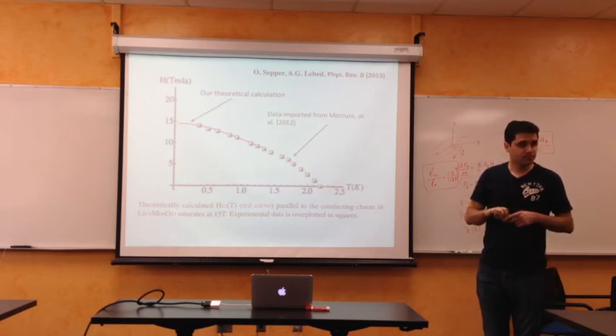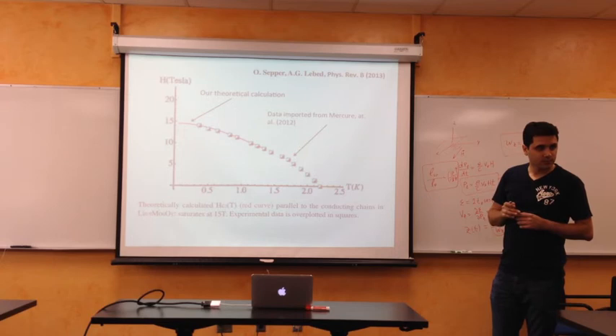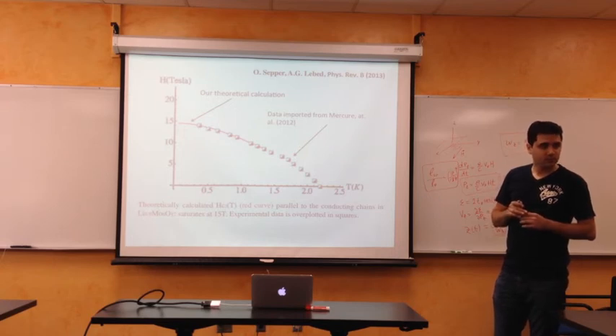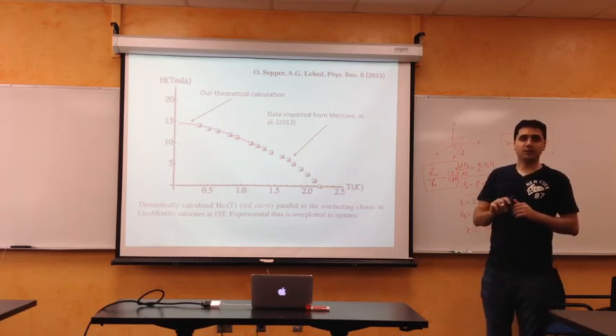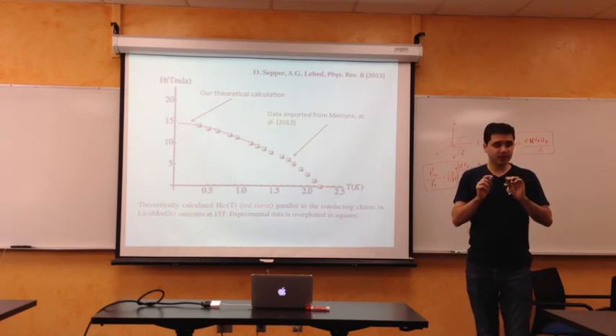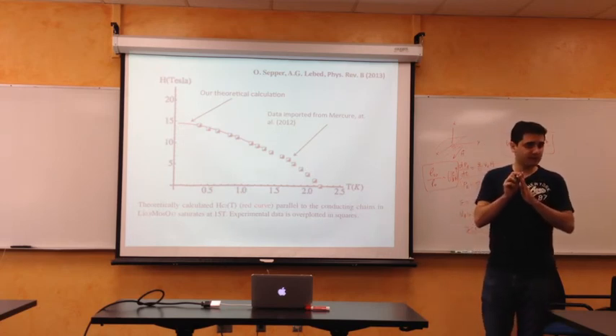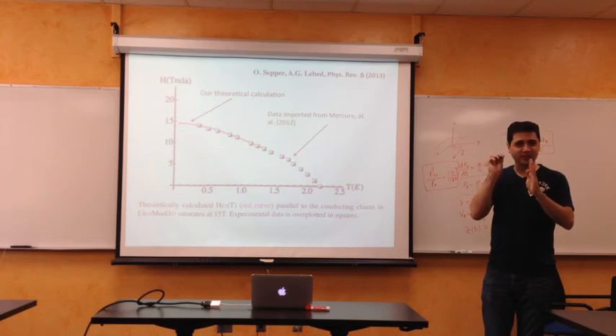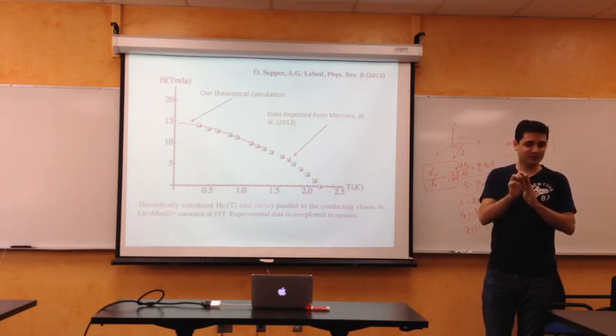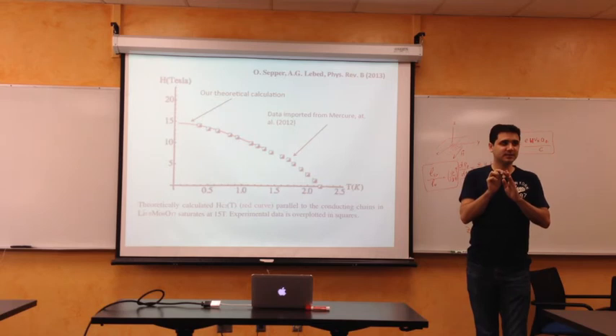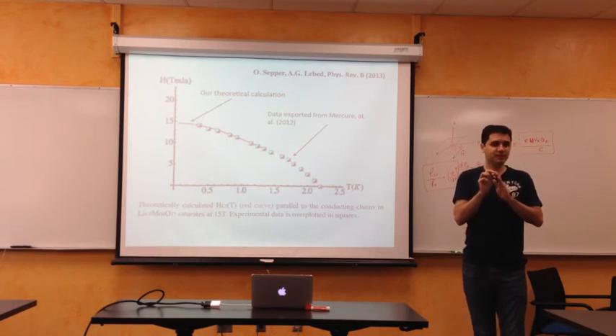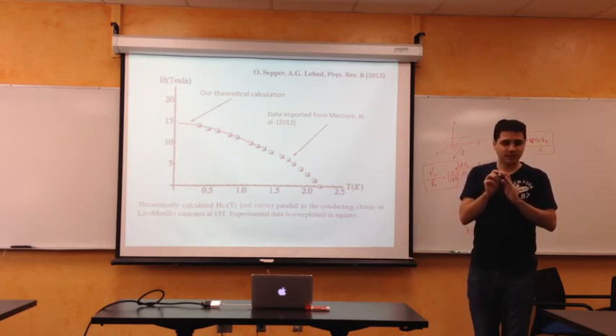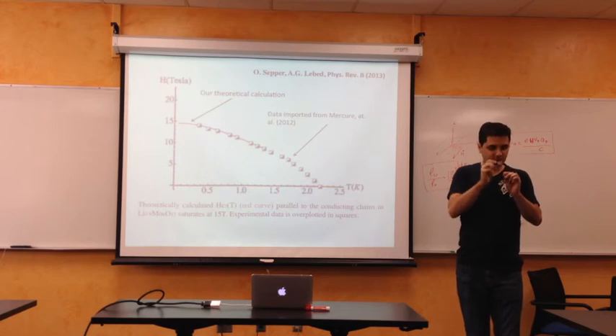Just the fact that HC2 is very high implicates that it's triplet. The fact, the combination that HC2 is 5 times bigger than HP, and the fact that this HC2 is parallel to the chains. Because the parallel case is difficult in the sense that because the interchain electron velocities are small, the Lorentz force is zero.